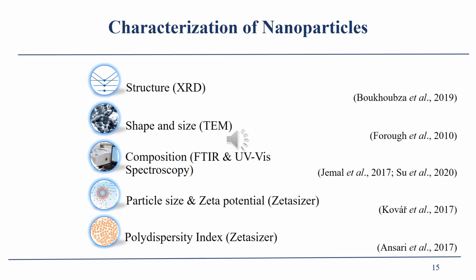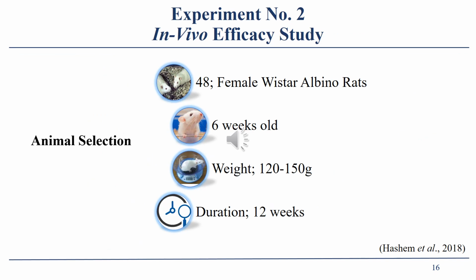To determine the stability and particle size in a solution of the nanoparticles, a zeta sizer will be used to determine zeta potential and particle size. To determine whether the particles are homogeneous or not, the polydispersity index will be determined by using the zeta sizer. Experiment number 2 is to check the bioavailability and consequential effects of the folic acid coated iron oxide nanoparticles.